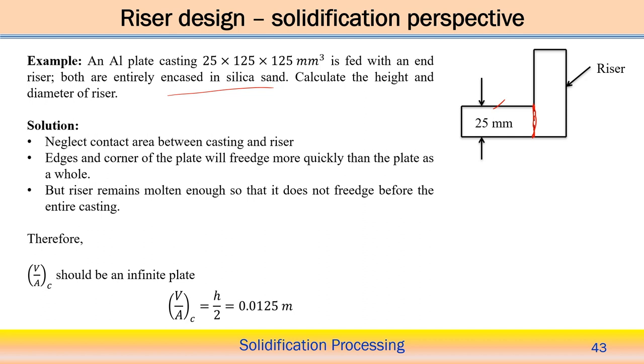First, we neglect the contact area between the casting and the riser. Although there is some contact area, we can neglect it, in the sense that all the riser surface area is responsible for losing heat. The edges and corners of the plate will freeze more quickly than the plate as a whole. Definitely the edges and corners will be thinner, but we are not considering which part will solidify first and which second; we neglect these factors, and as a bulk we consider the solidification of the riser and the casting. But the riser remains molten long enough that it does not freeze before the entire casting, so at least we will be able to supply molten metal into the cast volume as the shrinkage happens. So, assuming all these things, we can start the solution.